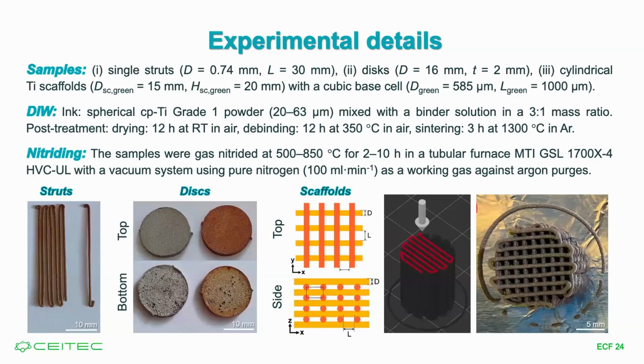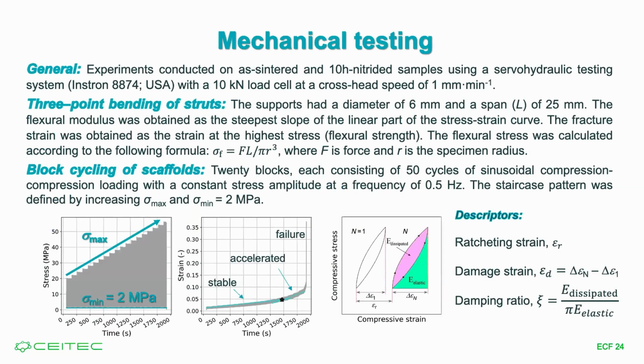So the experimental program is quite complex, but we prepared single filaments or struts, as shown here, to be tested in 3-point bending, then discs for hardness and some other analyses, and full scaffolds for cyclic loading, as shown here, where we basically cycle between constant minimum value and then increase maximum level. This block has 50 cycles, just to get the response and see how the response of material changes, which here is described by the shift of the hysteresis curve, ratcheting strain, and change of the width of the hysteresis curve. So this describes the changes in stiffness of material and the energy consumed during cycling.